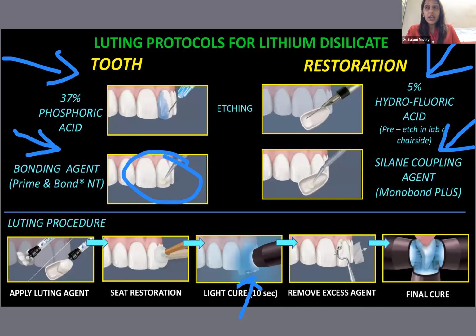to give more room, you just need to load the basic paste and then you light cure it finally. So that's what is your protocol you need to follow for a particular lithium disilicate. Again, I emphasize pre-etch with 5% hydrofluoric acid, done in the lab or the chair side, followed by a silane coupling agent, has to be applied to the intaglio surface of a lithium disilicate. And obviously your basic protocol on the tooth has to be followed with the kind of system or the bonding luting agent that you are using.